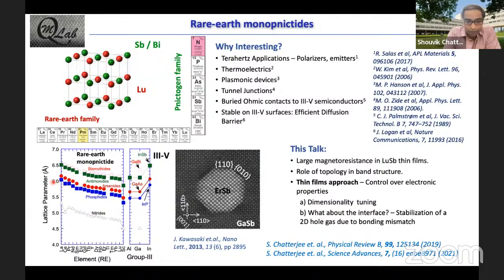You can see I'm plotting the lattice parameters of many different compounds, and they have quite a good lattice match for many different 3-5 semiconductors. So one can actually utilize this particular aspect to create biaxial strain to control their electronic properties.